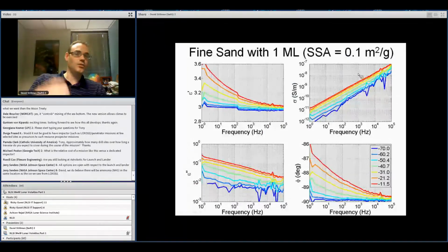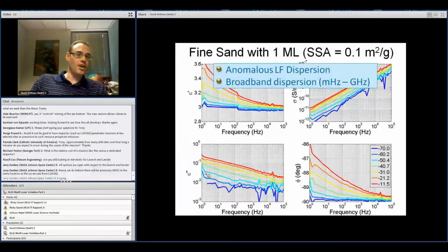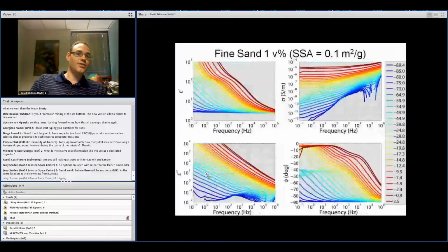This sand, with a monolayer of water, has a specific surface area of 0.1 meters squared per gram, where lunar regolith would be almost one. And so you can see at this low frequency, we're getting this dielectric relaxation, but more specifically, it's called a dispersion. It's very broadband. It extends from the millihertz all the way up to the gigahertz. It's very temperature dependent, as you see. And so this allows us to show that we do have one monolayer on that sand. And we call this an anomalous low-frequency dispersion, or the LFD for short.